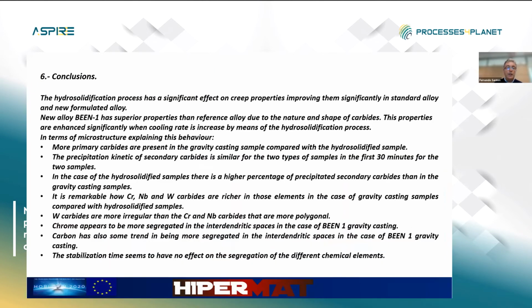Well, let's say that hydrosolidification has a significant effect on creep properties, improving them significantly, in both cases, in the standard alloy and in the newly formulated alloys. Also, the chemical composition modification that we have performed has a significant effect on creep properties, and in fact, it affects a lot the creep growth rate.